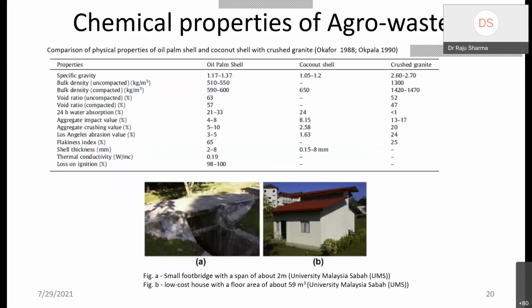Okay, now if you're looking into the oil palm shell waste and coconut shell and you compare their properties, you will find that the specific gravity of the oil palm shell and coconut shell is lower than the crushed granite. So if you replace the granite, automatically you are taking the higher density material out of the system and putting lightweight material into the system. So the final product will be a lightweight material, having a lower density than normal concrete, right? Then you can see other combinations there as well.